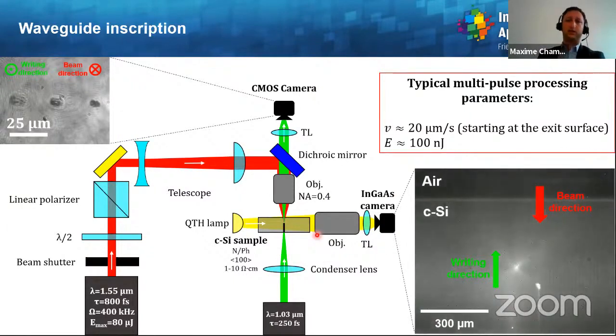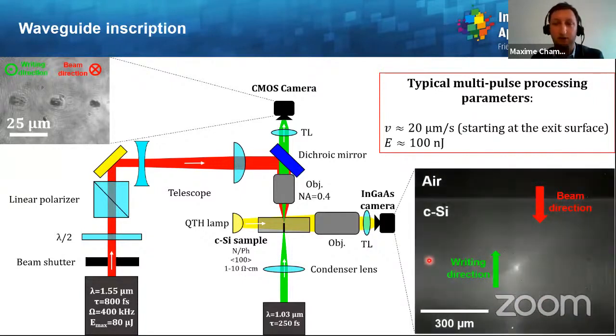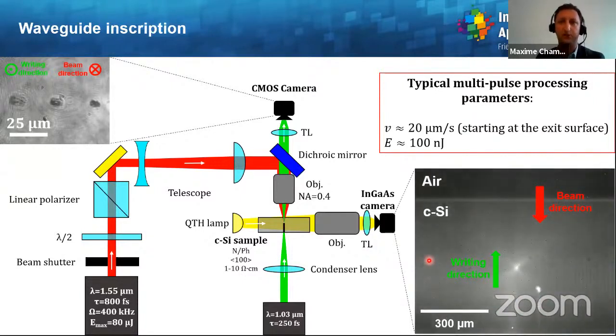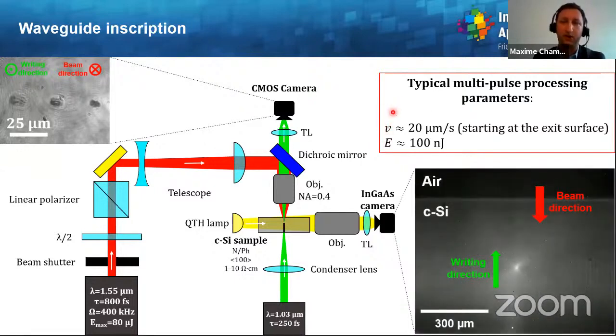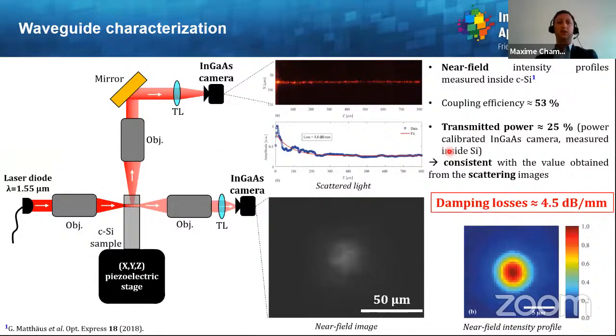And with the first infrared microscope in a transverse way, one can see the process. So the idea is to write the waveguides from the back surface and move the focus towards the laser, to take advantage of the brittleness of the exit surface. The typical processing parameters are a feed speed of 20 micron per second and pulse energy around 100 nanojoules. Concerning the waveguide characterization afterwards, this is done post-mortem.